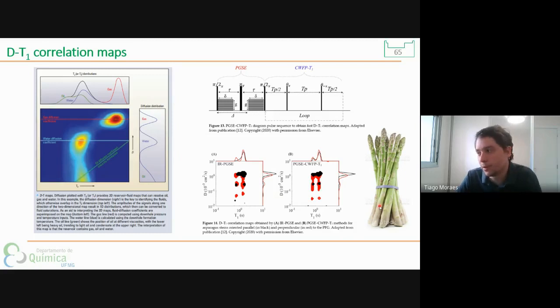Of course, you can imagine that the diffusion of the molecules in this direction of the asparagus is much easier than in a perpendicular way. So they did an experiment and showed it in this type of map. You see here in black the map for the asparagus parallel to the magnetic field, and here in red when it is perpendicular. So what I want to show you here is that with this type of map, you can determine information about the structure inside your sample, right? For example, in asparagus, very interesting one, right?